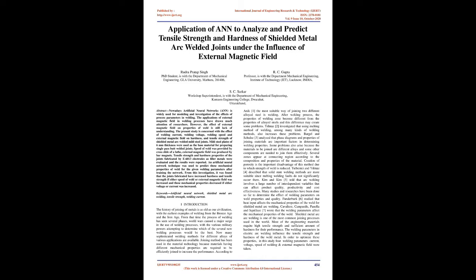From this investigation, it was found that the joints fabricated have increased hardness and tensile strength if either speed of weld or external magnetic field was increased, and these mechanical properties decreased if either voltage or current was increased. Keywords: artificial neural network, shielded metal arc welding, tensile strength, welding current.